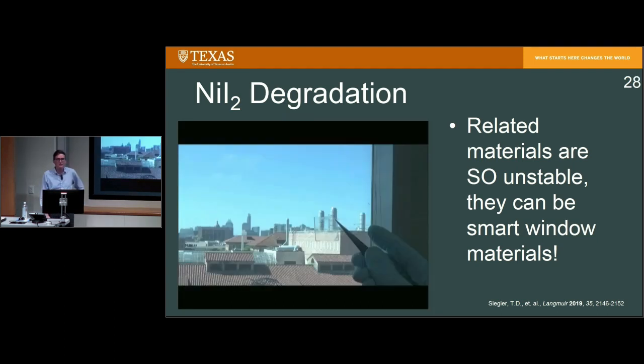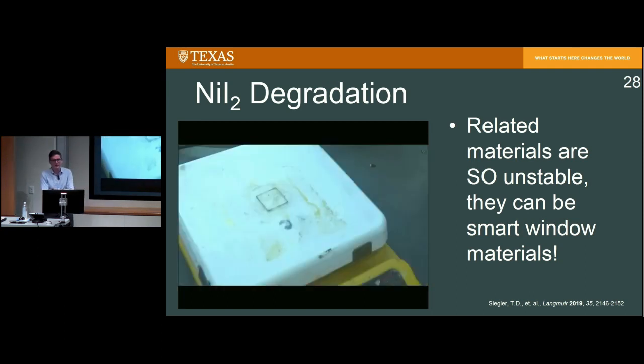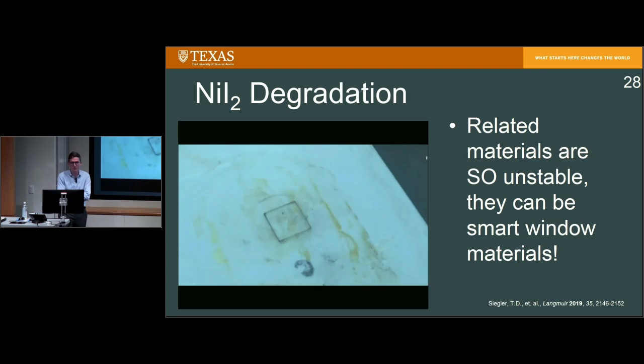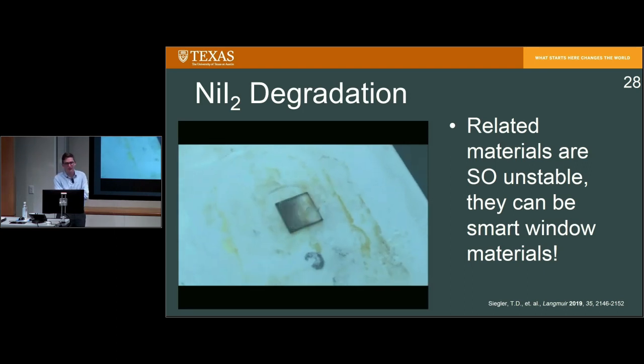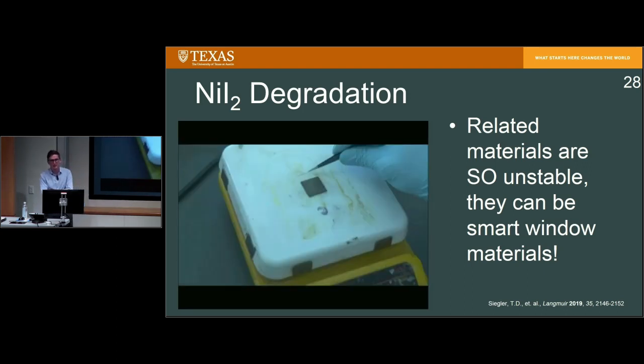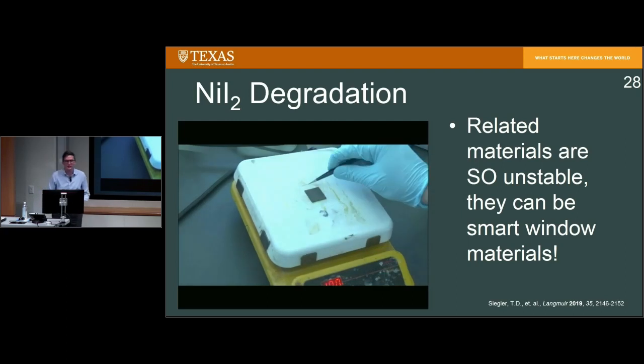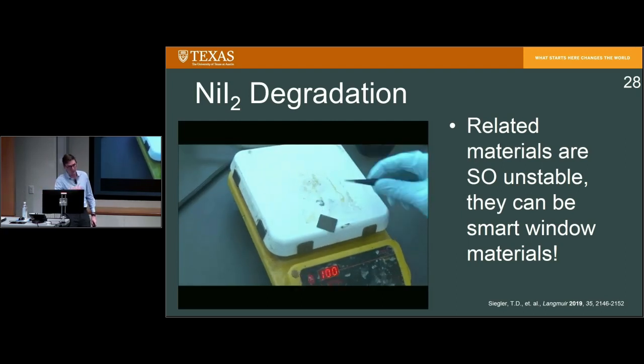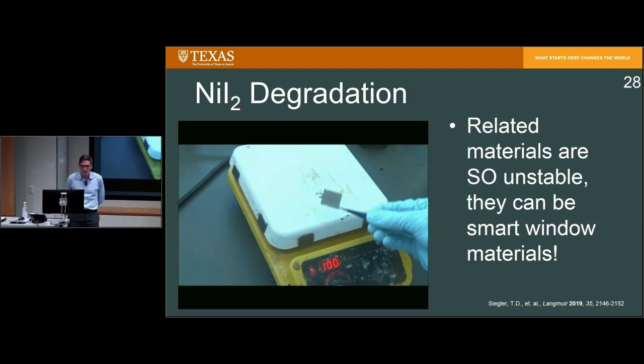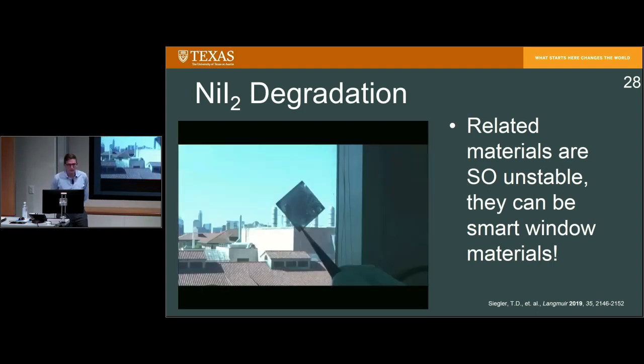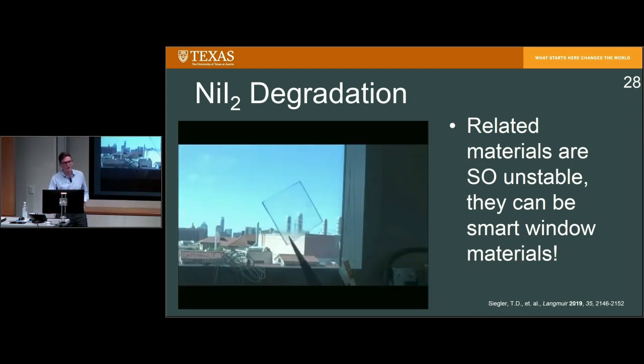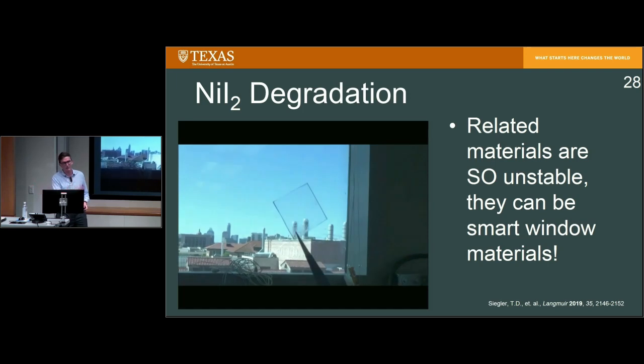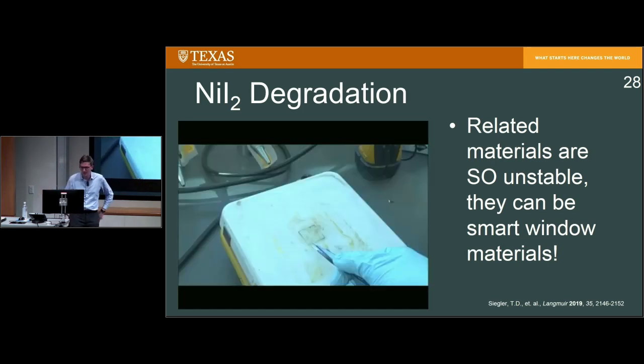But unique to this material versus what perovskites normally do, you can actually take the water liquid that precipitates on the film, and you can revert back to the dark phase of the material, the nickel iodide. And so this could potentially be used for energy efficiency applications with smart windows that require color neutral transitions between completely clear and completely black states.